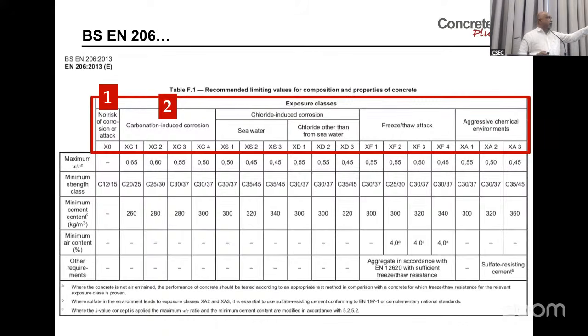But if you have corrosion induced by seawater, then you see the water cement ratio is limited to 0.5. Other than seawater also, sometimes you have a maximum of 0.5. Then freeze-thaw, we don't have much here, but both heating and cooling are very similar to that, though we don't go to that extent. And aggressive chemicals, these are the most common ways. So these are the recommended maximums. You have to be below 0.5. That's why I told you that if you want to design very good structures, please be around 0.4.